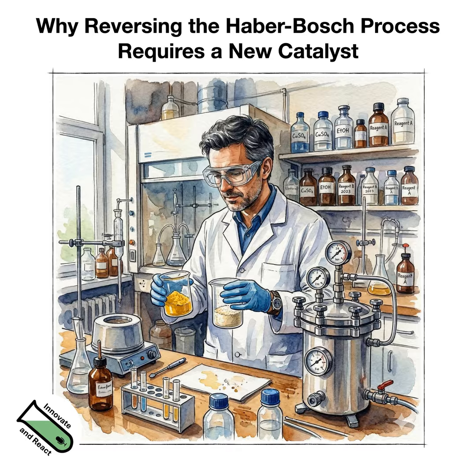The surface area doesn't necessarily need to be high, but when we calcine it to the oxide and then reduce the metal fraction in a subsequent step, this larger particle can, and that's more like a top-down structuring, create smaller pores in itself. It will fall apart is not the right word, because we want it to be mechanically strong. So it does not fall apart, but it becomes porous in that process.